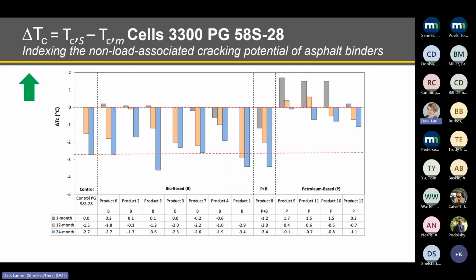Here we have results for the delta TC, where we can be evaluating the cracking potential of the asphalt binders. You can see that, by the results of the binder itself, the section has a very good binder, and because the pavement was brand new, the delta TC after 1 month for the control binder was 0, which is considered very good. So the placement of this treatment would be an additional improvement for the binder. And you can see that regarding the bio-based and the petroleum-based, the petroleum-based, as we saw for the low temperature PG and high temperature PG, resulted in the biggest improvement per se in terms of delta TC for the neat binder section.